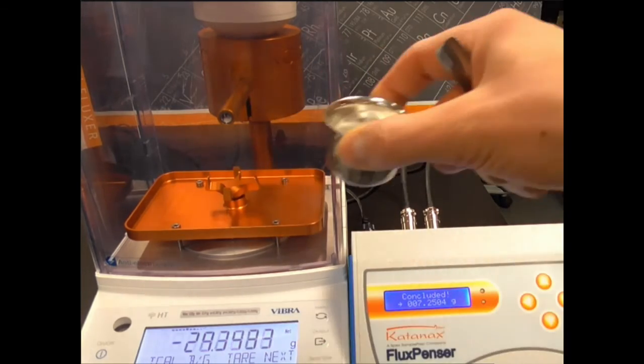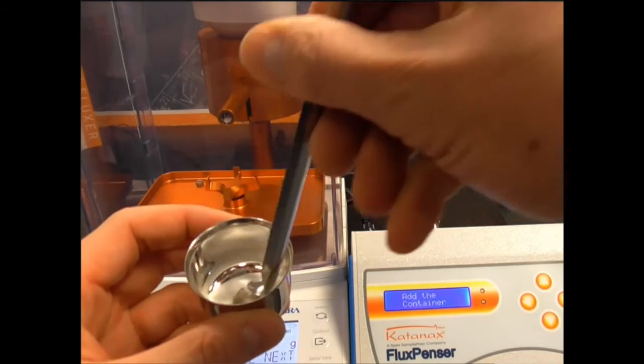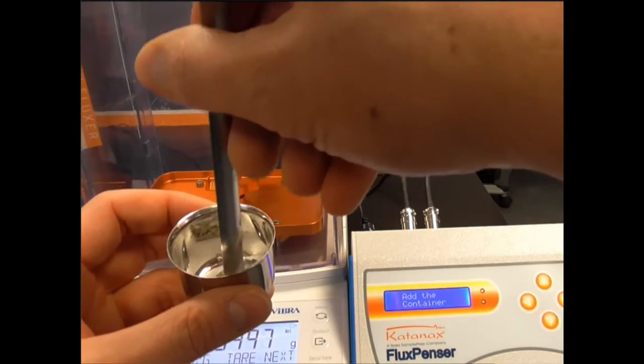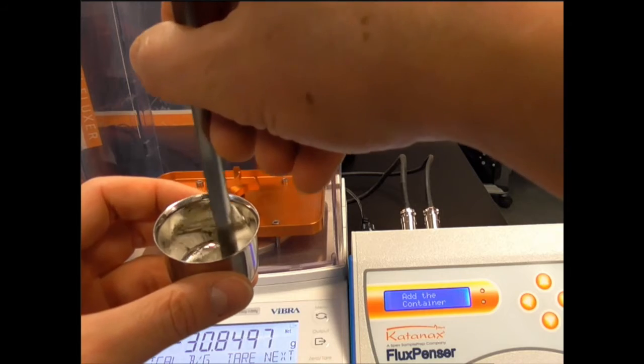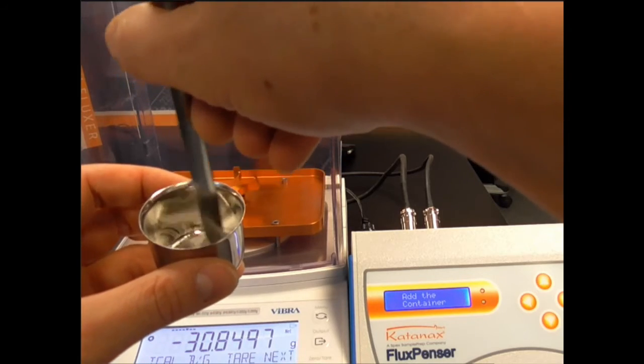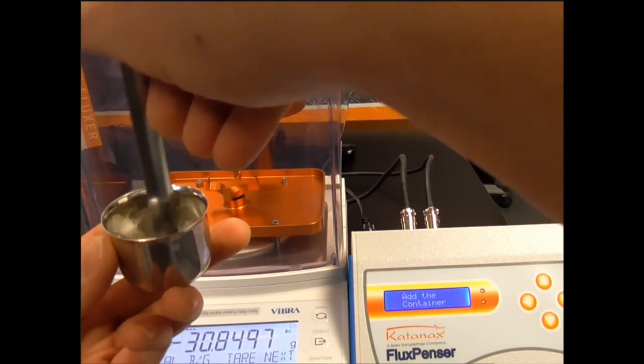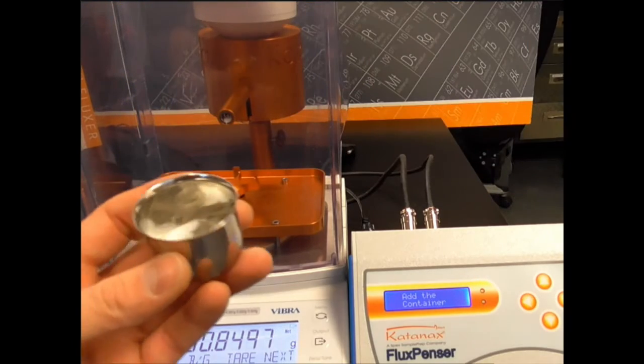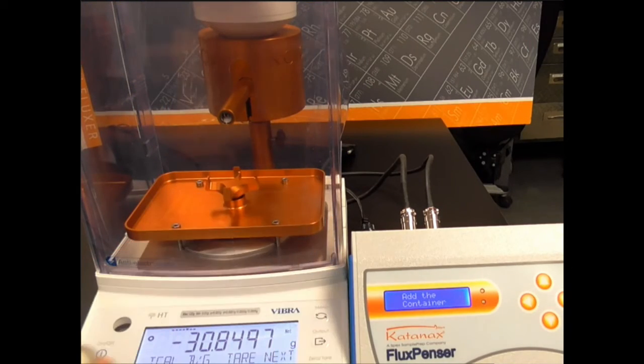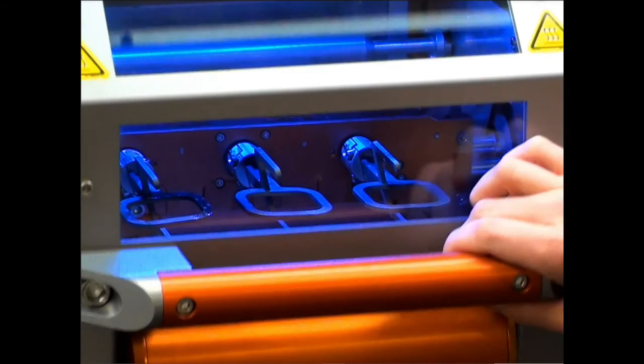I will take my crucible and mix a little bit. It's always recommended to mix the flux and sample together. This can have a huge influence on the fusion digestion afterwards, so we mix a little bit like this. Some samples are more sensitive to the proximity between flux and sample, so just keep this in mind. We will now transfer to the instrument itself, where we will just put everything in place.